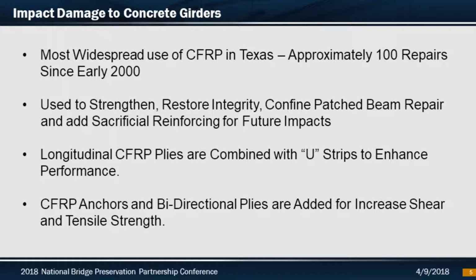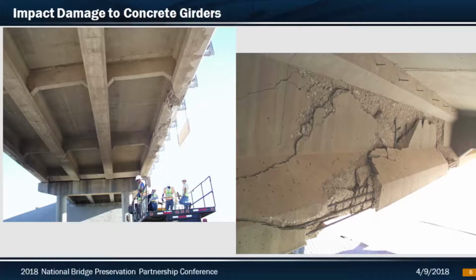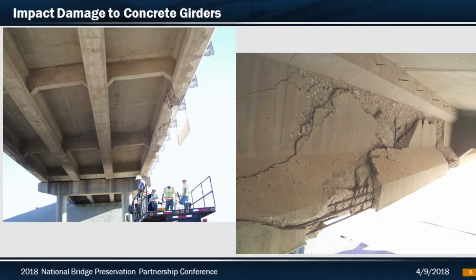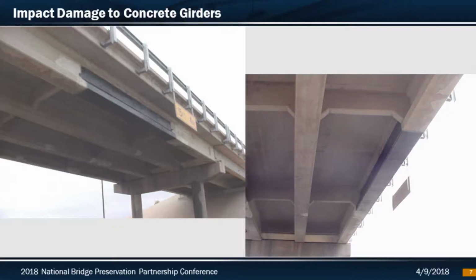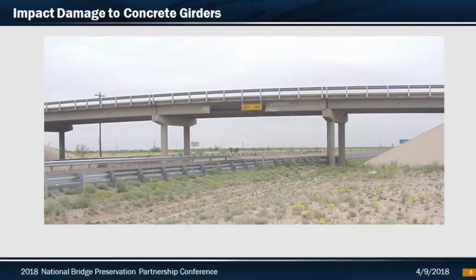This was one of the earlier age bridges hit, I believe in 2003 out in Odessa. A lot of oil and gas, so we had plenty of oversized loads, probably no permitting. This beam was impacted, rupturing a lot of the web and flange. At the time it would have probably been considered a full beam replacement, but it was determined we could go ahead and do the beam repair in addition to the CFRP. So we did the longitudinal strip on the bottom flange combined with the U-wraps and opened it back up, saving many days, obviously not having to repair the whole beam and deck. I think it was 5 days to get it back open. Minimal cost compared to replacing the beam.